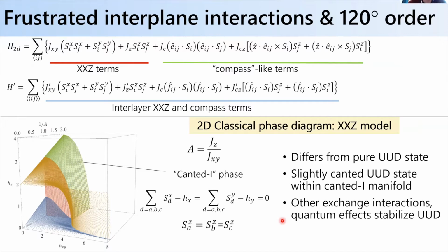Okay, good. So basically the next step, this was led by Leon Balents' group. Basically, you can look at all the symmetry allowed terms in the magnetic Hamiltonian, and they looked at both the allowed exchange within the plane, so this is within the triangular lattice, but also an interplane term, which they called H prime. And basically for their spin wave model, they just used this first term, the two-dimensional XXZ terms.